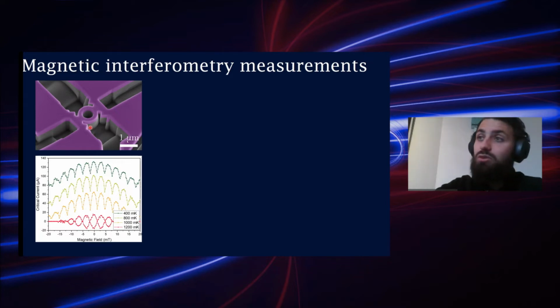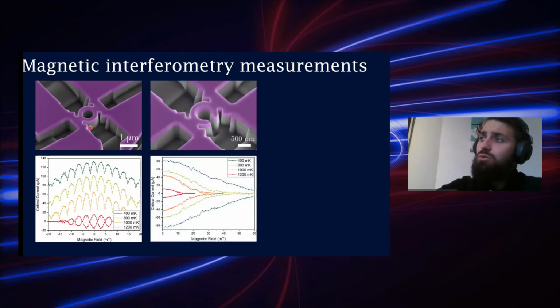At least that is what you would expect. This is not something we see, but this can be explained since the width of the arms of the ring is roughly 3 to 4 times the coherence length. And since you're dealing with these length scales, the Fraunhofer interference pattern is turning into a Gaussian decay. And when we fit these with Gaussian functions, they are definitely Gaussian.